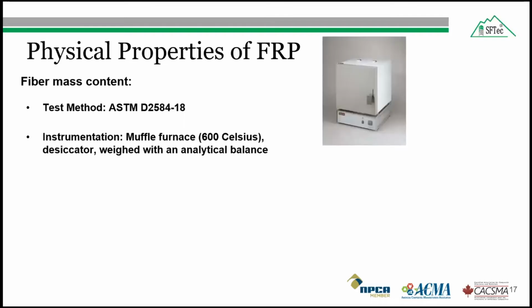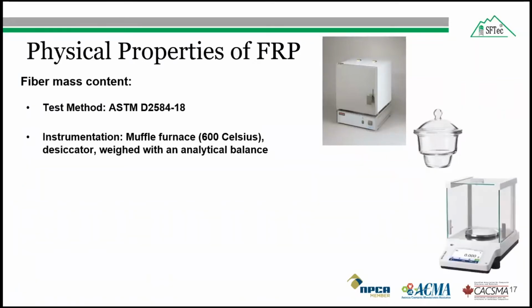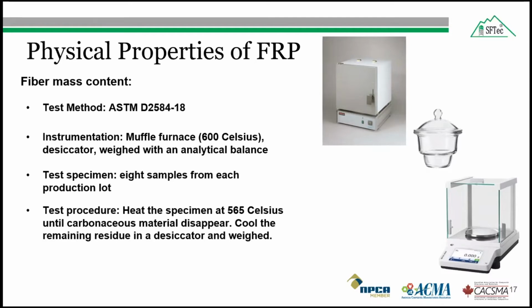And the instrument used in the test were muffle furnace, which are capable of maintaining 600 degrees Celsius temperature, and a desiccator to cool the specimen. The specimen were weighed with an analytical balance to 1 milligram precision. So as I told you earlier, a total of 8 samples from each production lot were tested, and the 1 inch fiber reinforced polymer samples are heated at 565 degrees Celsius until the carbonous material disappear, and then the remaining residue is cooled and weighed.